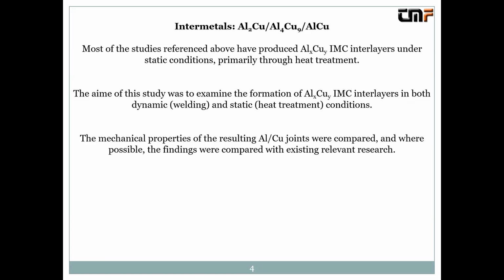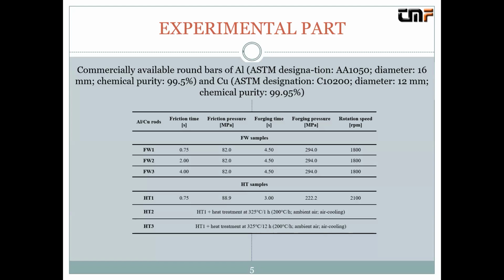So we varied the parameters during the welding in order to obtain different heat inputs in the welding joints, so as to produce a whole variety of types of intermetallic layers. Two sets of the welded joints were made. The first one for, let's say, the dynamic testing, and we varied the friction time. The friction pressure, forging time, forging pressure, and rotation speed were the same. The second set was the heat-treated samples. They were made with parameters similar to those of the welded joints. Here we wanted to provide as thick an intermetallic layer as we could.